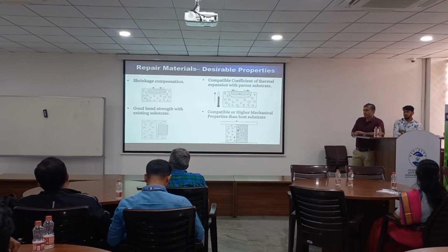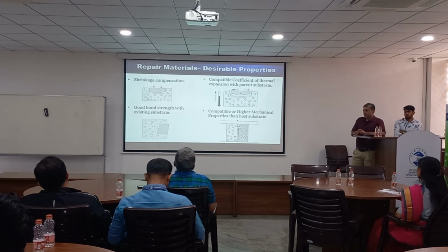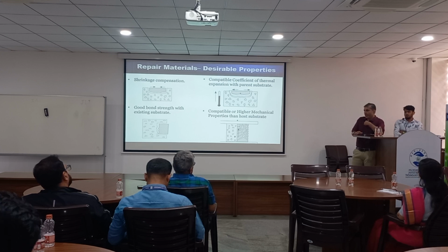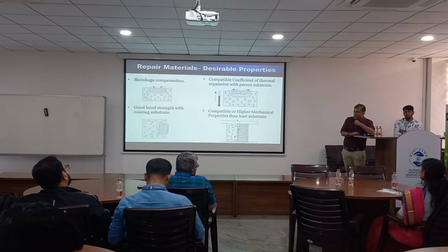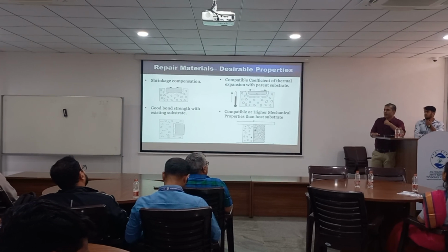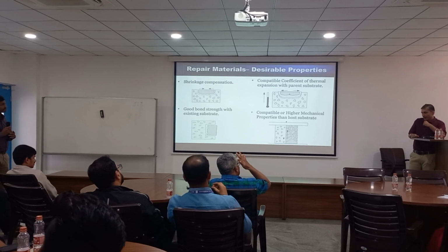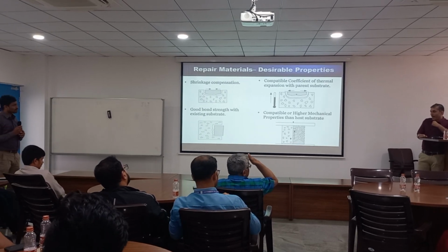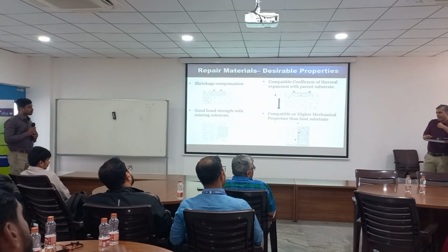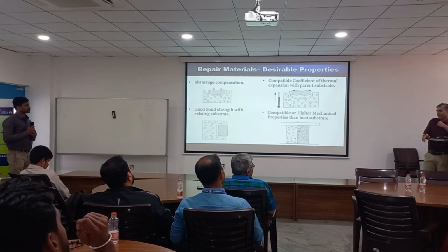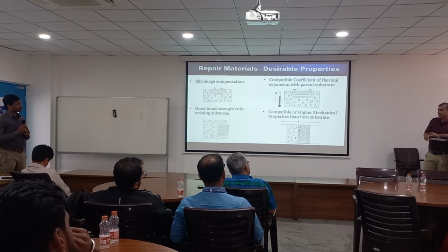And also, generally when we coat the reinforcement with marine epoxy and similar materials, how will it affect the bond? One thing we need to understand is that the presence of epoxy will reduce the impact of corrosion, but it comes at a risk. The bonding between the concrete and the steel will not be that good. So the designer has to take into account the loss occurring because of the reduction in bond, and carry out the design accordingly.